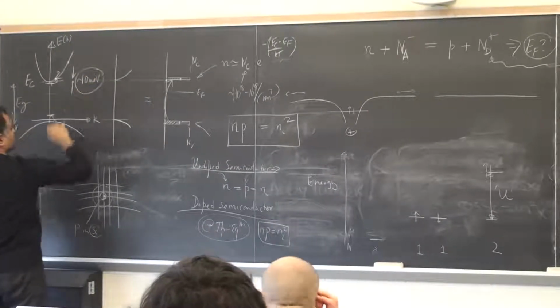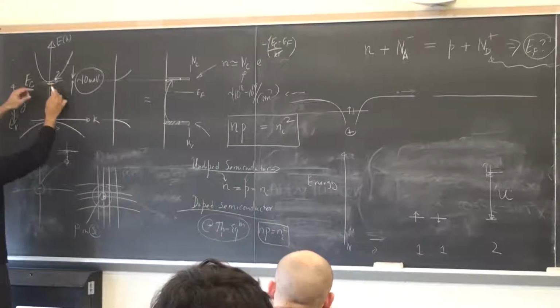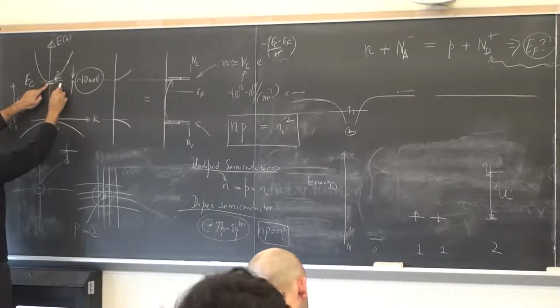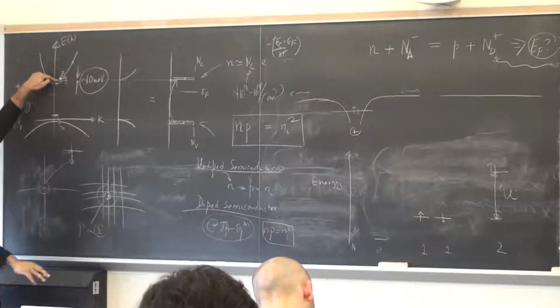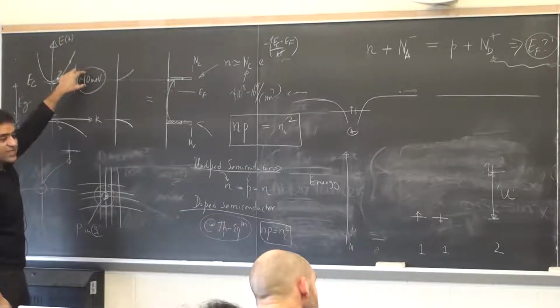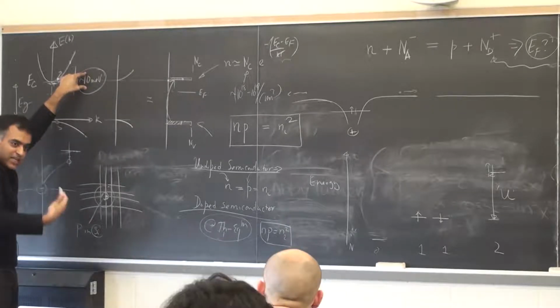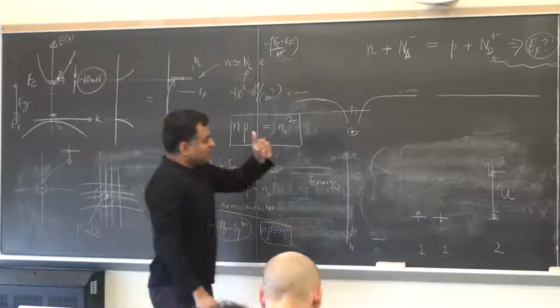This is a good dopant because the kind of dopant I would choose at room temperature is such that room temperature gives me enough kick that the electron is kicked out into the conduction band. That's what I kind of need. So room temperature is 26 millielectron volts, so 10 meV can take care of that. But it will not be completely ionized. There will still be some stuck in the donor.